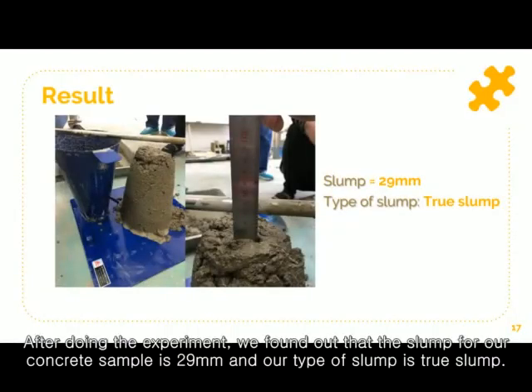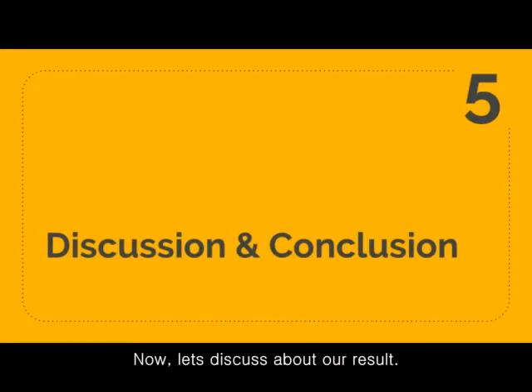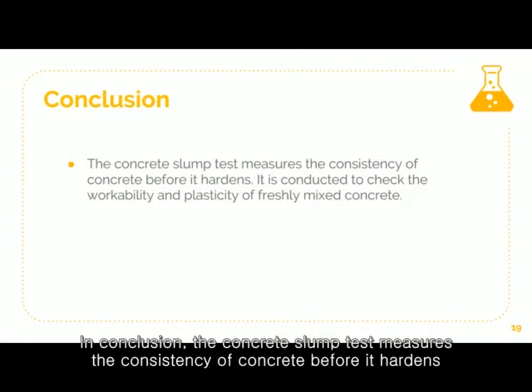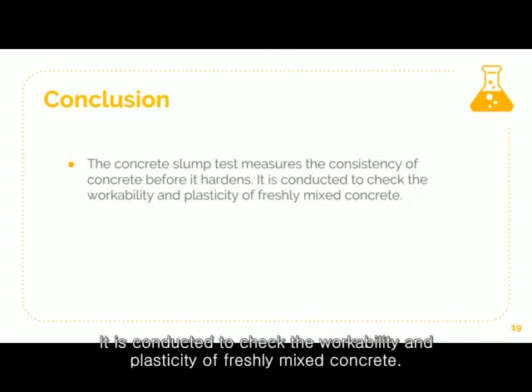After doing the experiment, we found out that the slump for our concrete sample is 29 mm and our type of slump is true slump. Now, let's discuss our result. In conclusion, the concrete slump test measures the consistency of concrete before it hardens. It is conducted to check the workability and plasticity of freshly mixed concrete.